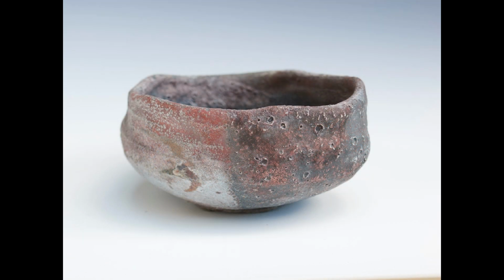What happens with these pieces is that this piece was a green glazed piece. I'll show you an example of what it looked like before it went into the kiln. It was glazed with green Oribe glaze. But the glaze turns red and it turns turquoise, and it bubbles up. The piece itself is placed upside down on a brick under the firebox, and it begins to get buried in embers. It heats the bowl up, the glaze starts to melt, but then it gets buried in embers. And those embers are surrounding it and creating little micro zones of reduction. So little oxidation, little reduction. So you get a tremendous variance of color across these pieces.